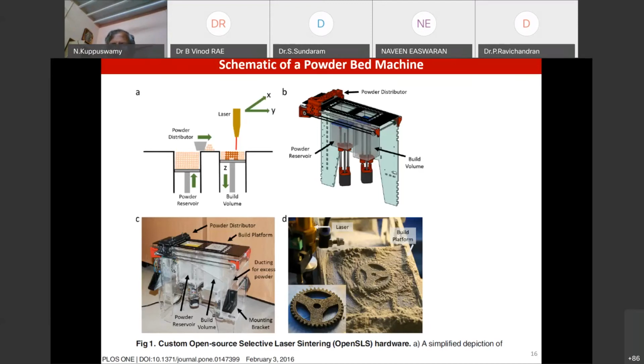The difference between SLS for nylon and that for metal is typically in laser power. For nylon, I will show you further up, you can have as low as 5 watts or 10 watts. For metal, the minimum would be in the region of 250 watts. I would say today, with laser prices being low, we'll go with 500 watts, typically. Okay, this is the backbone of a typical powder bed machine.